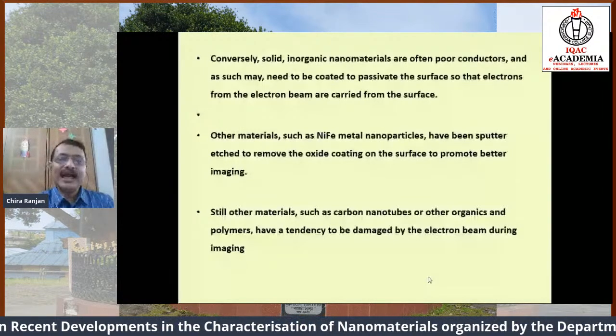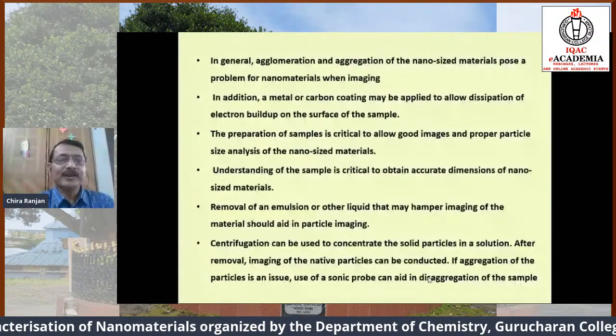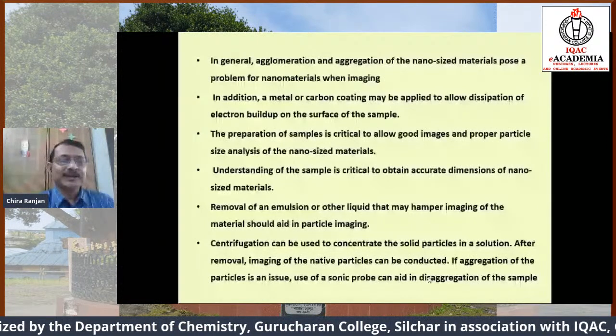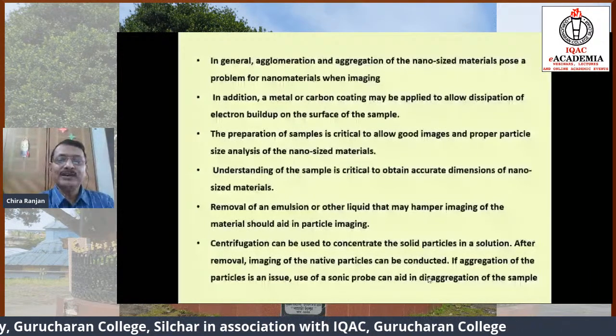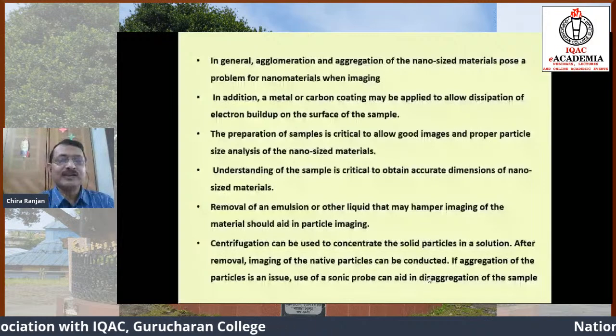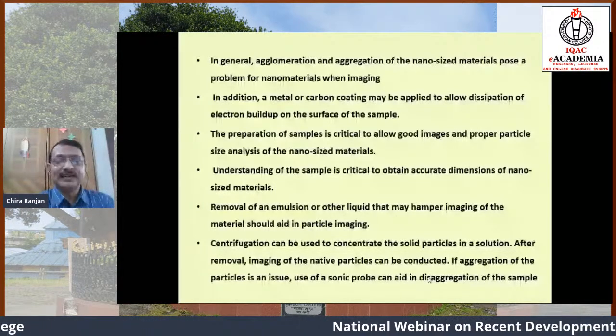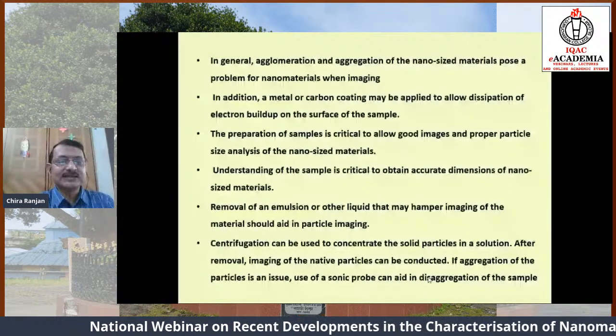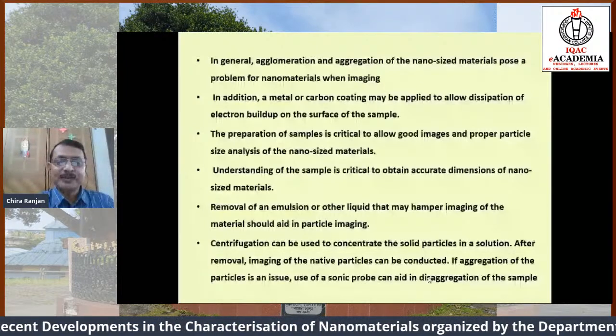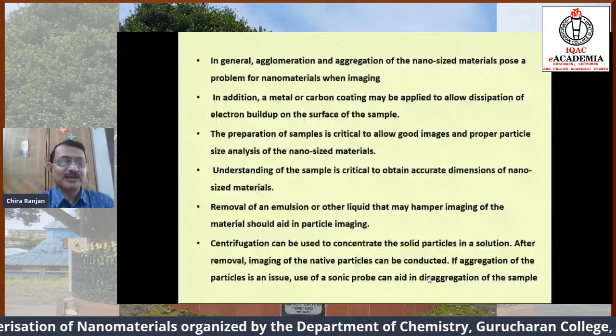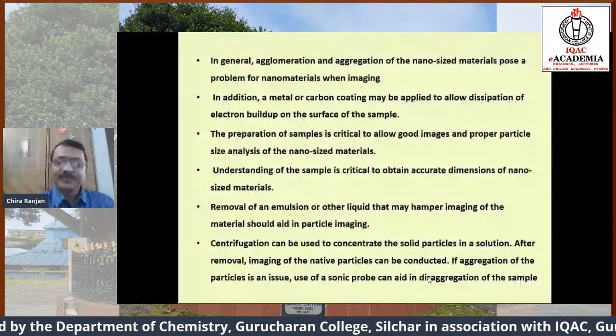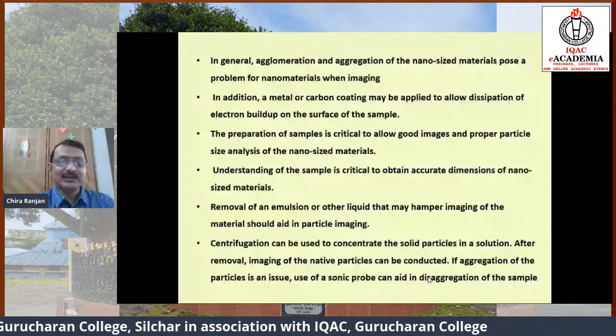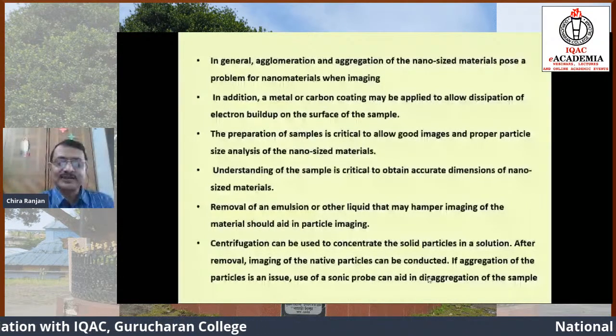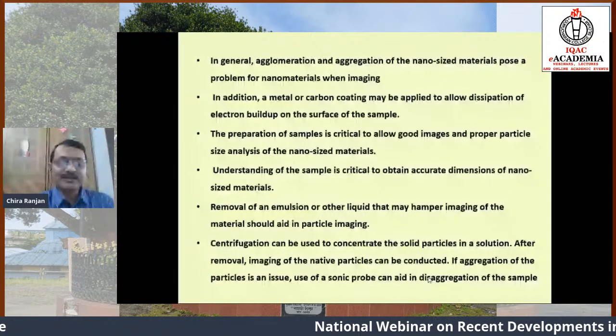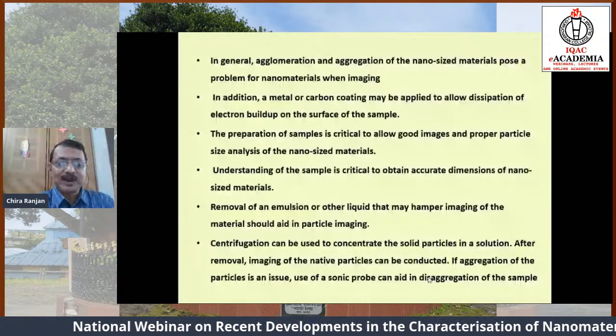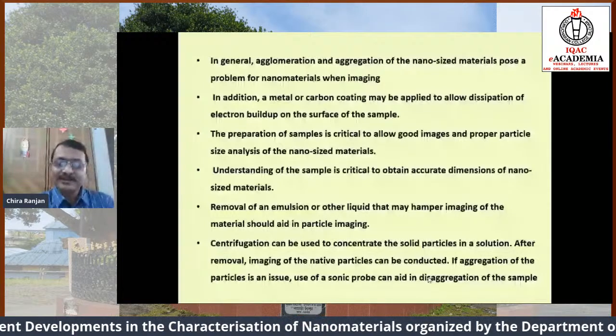In general, agglomeration and aggregation of the nano-sized materials pose a problem during imaging or viewing. In addition, a metal or a carbon coating may be applied to allow dissipation of electron buildup on the surface of the sample. The preparation of the sample is critical to allow good images and proper particle size analysis of the nano-sized materials. Understanding of the sample is critical to obtain accurate dimensions of nano-sized materials. Removal of an emulsion or other liquid that may hamper imaging of the material should aid in particle imaging. Centrifugation can be used to concentrate the solid particles in a solution. After removal, the imaging of the native particles can be conducted. If aggregation of the particles is an issue, use of a sonic probe can aid in disaggregation of the sample.